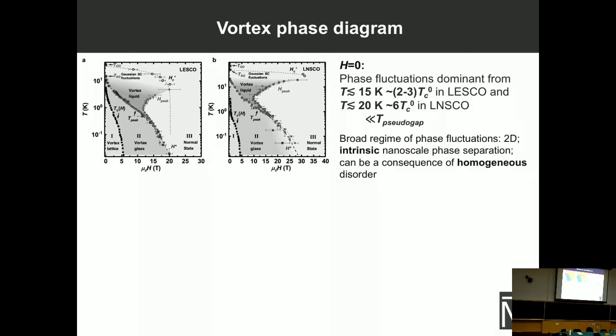So what have we learned from here? Okay, so let's see first what happens at zero field. We find the onset of the phase-fluctuation-dominated regime at temperatures that are several times higher than the zero field TC. So this is in contrast to what some people have been claiming, but nevertheless, these temperatures are still much lower than the pseudo-gap temperatures for this material. So in these experiments, we do not find evidence of pairing at such high temperatures.